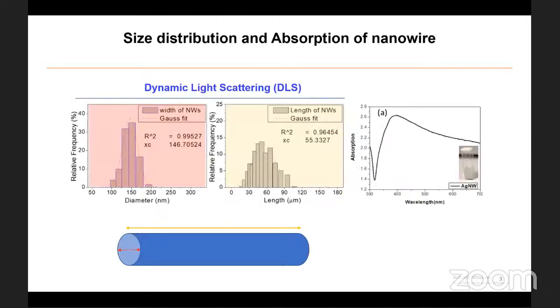At first, we synthesize silver nanowire by wet chemical approach, and the dynamic light scattering analysis shows the average diameter of nanowire to be about 115 nanometer and length to be 15 micrometer. Our synthesized nanowires show a broad absorption spectrum spanning over the entire visible region. So the broad absorption nature of our nanowire is suitable for PEF application.